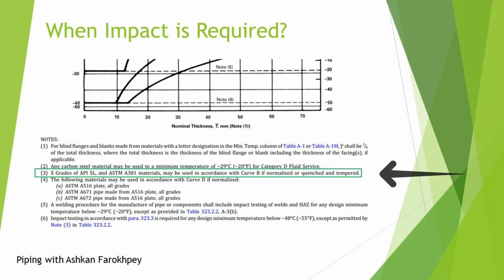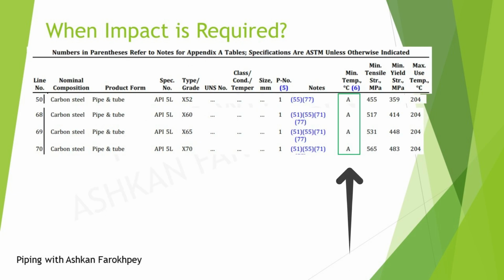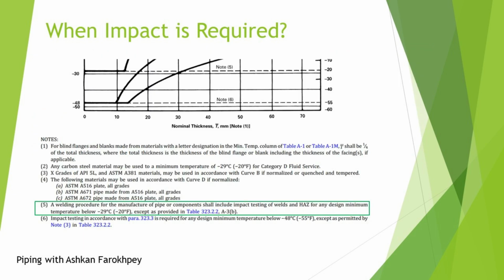Or in Note 3, as an example, the code is telling us that if your API 5L X-grade materials are normalized, you can use curve B for impact testing determination, while these materials are all marked with letter A in Table A1. Note 5, for example, says that all the materials with minimum design temperature below minus 29 degrees centigrade require impact testing of the weld and heat affected zone by the manufacturer, except as mentioned in Table 323.2.2. So, don't forget to read all the notes exactly.